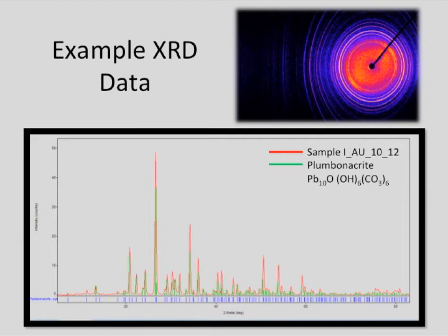The data for this plumbonacrite from one of our samples is quite beautiful. You see a lot of very nice bright bands for the diffraction pattern, and then we match those to library spectra and assign which phases are present. This happens to be a single phase sample. If we had multiple phases, we have the ability to subtract out what we've positively identified and do multiple phase analysis. It's quite a nice system.